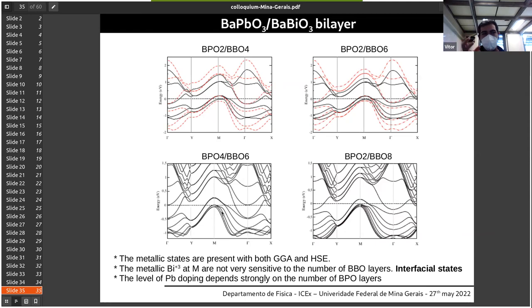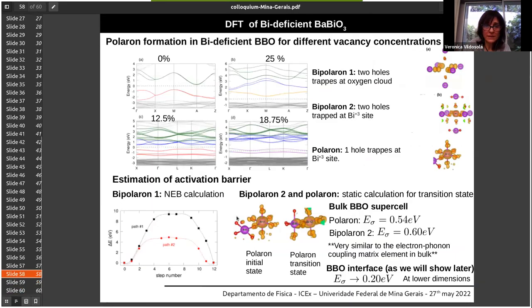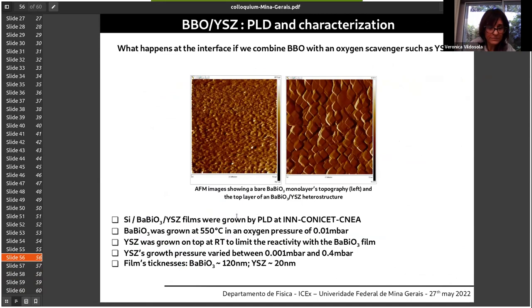The main idea is that you have high electron-phonon coupling, so you induce TC at the interface. But can you connect directly the charge transfer with the coupling? Yes, because in the case of the bilayer, it is true that as compared to bulk, the coupling is smaller because you have only one operative collective mode, the stretching instead of the breathing distortion. You have only the stretching. Okay. But what you have is a large density of states, larger than in bulk. So what we, and the coupling, I am doing some, sorry.